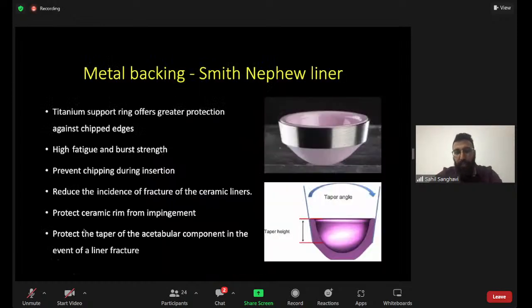Again, there are some companies like Smith & Nephew which provide metal backing. What this metal backing essentially does is provide a titanium sleeve to the rim of the ceramic liner, which allows easier insertion, protects the taper, and offers high fatigue and burst strength, thereby preventing chipping of the liner during insertion. It protects the ceramic rim from impingement on movement and also protects the taper of the acetabular shell in case of a liner fracture.